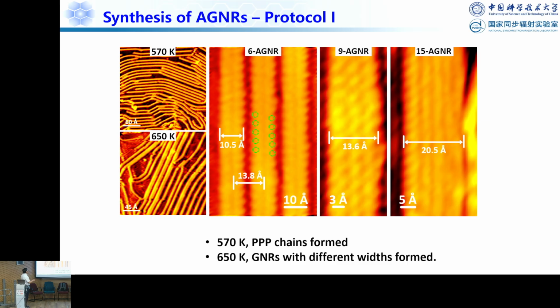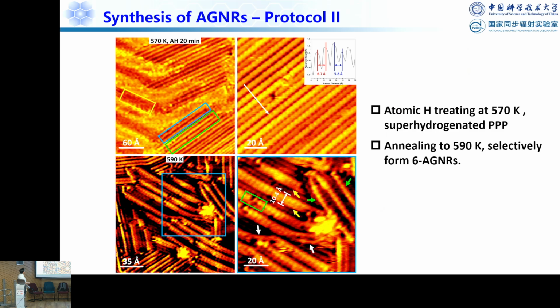This is a 6 armchair graphene nanoribbon, 9 armchair graphene nanoribbon, 15, and as you can see, some are broader, some are narrower. Okay, so if we put the atomic hydrogen on the surface, not only can we get rid of the bromine atoms with hydrogen, but you can also super-hydrogenate the PPP, and then with the temperature increased to 590 Kelvin, now you have only 6 armchair graphene nanoribbons formed on the surface. So why is this the case? Why only 6 armchair graphene nanoribbons?